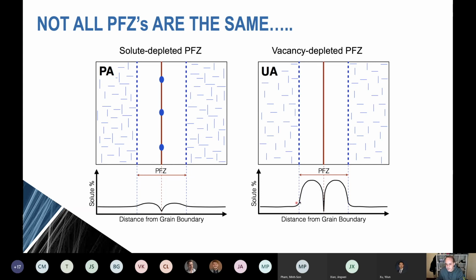Now, this is very interesting because if you start with this type of precipitate-free zone, and you begin to cycle the material, the plasticity is first going to localize in the precipitate-free zones. And if you can control this well, then in principle, you can drive dynamic precipitation in the precipitate-free zones and strengthen these regions to remove the mechanical contrast between the grain interior and the precipitate-free zone. And so this was the idea.